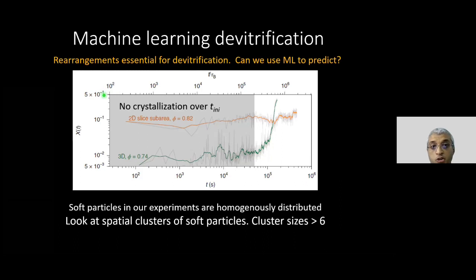Okay, and I'm going to do this machine learning analysis only over the initial 10^4 seconds of the experiment, where I did not see any crystals grow. So this is the time over which my sample still stays amorphous.